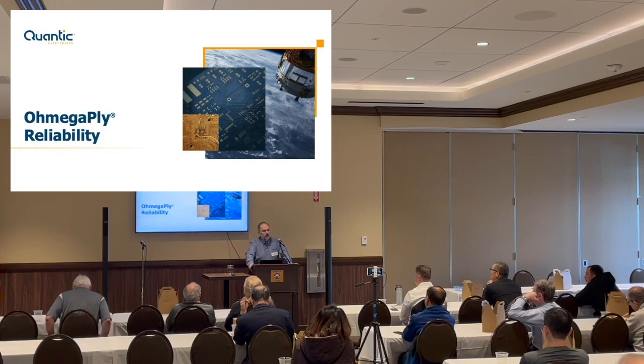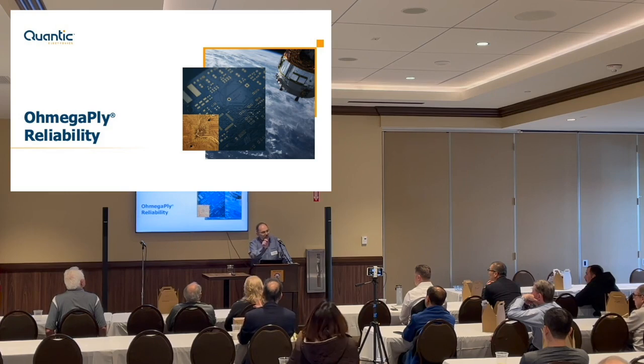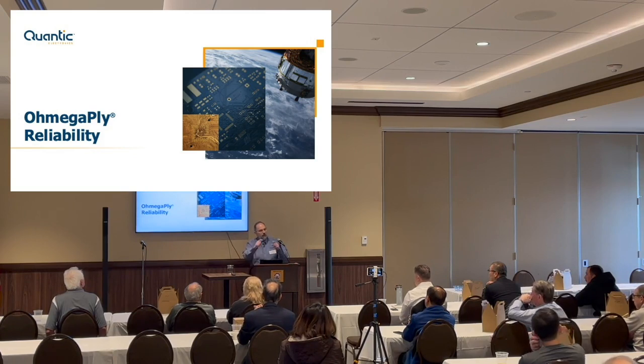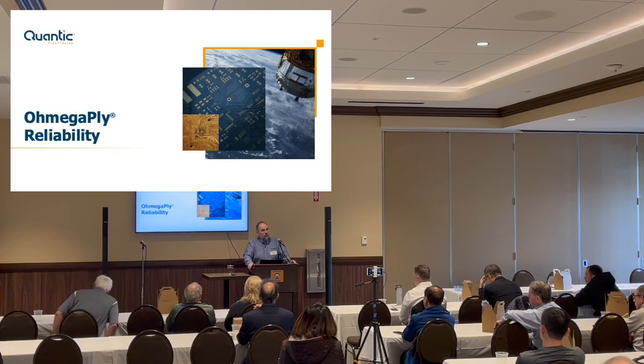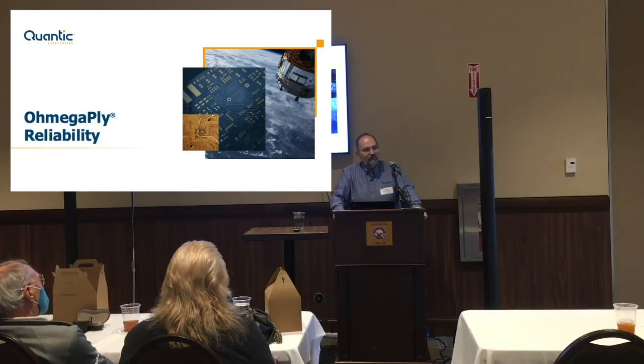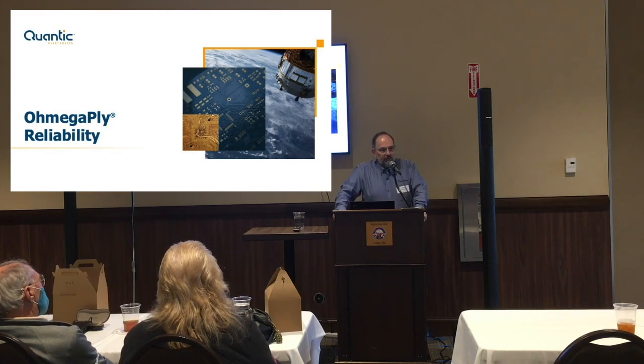And the tolerance also depends on the size. The bigger you can make the resistor, tolerance-wise, the better. When you make little tiny resistors, obviously any imaging is going to be an issue. But also, when you're laying it out, you have to make sure you have the right amount of overlap. You have to adjust for misregistration. So you have to design properly to give a little bit of extra room so you can make that connection. But again, with direct laser imaging, you've got better control of that anyway. Yes.